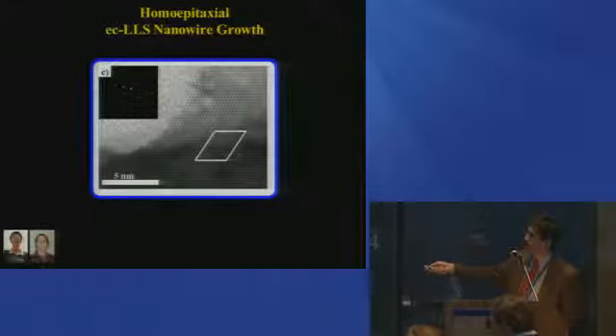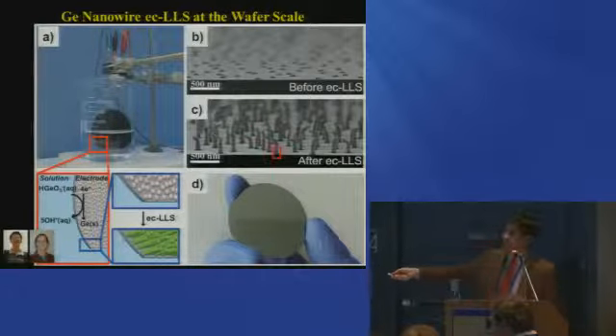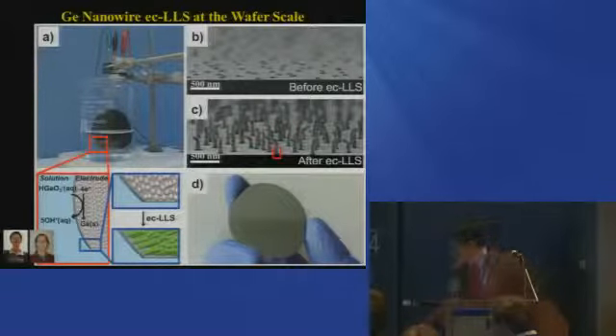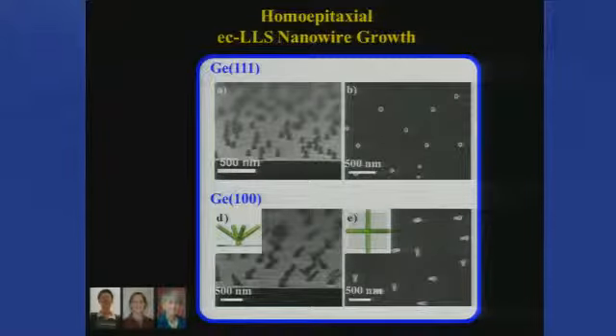Here's a cross-section of the foot of one of these nanowires on this substrate. You can see the crystallinity of the substrate extends directly into the nanowires that you're growing. Again, that looks like that at room temperature. These nanowires you can grow with epitaxy and heteroepitaxy, which in the semiconductor community is a big deal. And it's an even bigger deal that we're doing this at room temperature without any other tricks or buffer layers or anything excessive. We are just electrodepositing with a liquid metal and growing a crystal controllably that happens to be seeded by the substrate.